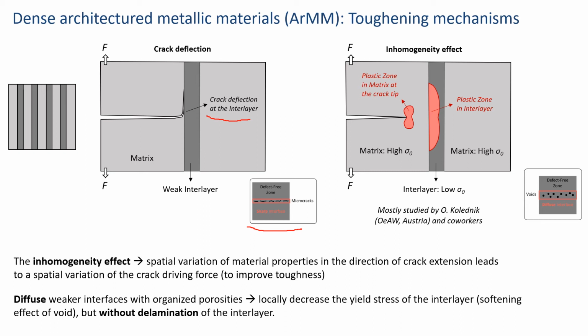So the inhomogeneity effect is based on the spatial variation of material properties in the direction of crack extension. And this is improving the toughness because the local variation is also introducing a spatial variation of the crack driving force, and this has been quite well studied by Kolednik and co-workers by modeling, and they have shown that this is a promising toughening mechanism.